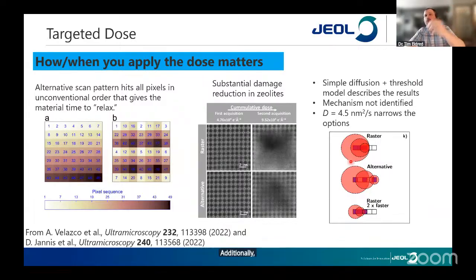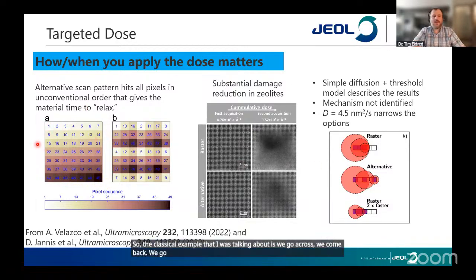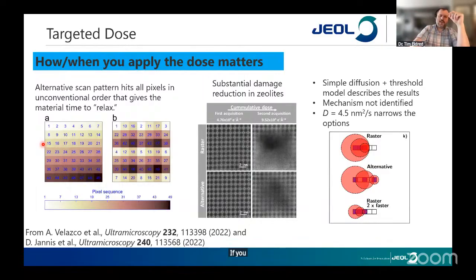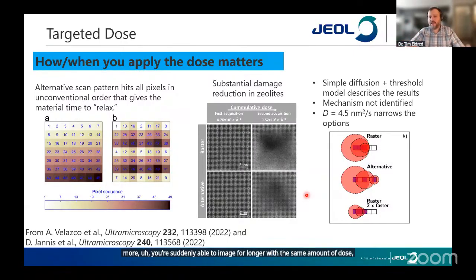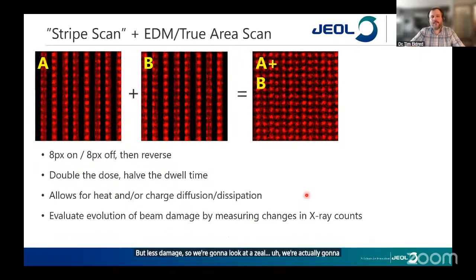Additionally, how you actually move the probe matters. So the classical example that I was talking about is we go across, we come back. We go across, we come back. If you instead go 1, then 2, then 3, 4, 5, 6, there's nothing inherently required about this type of scanning. And what they noticed is by changing where you apply your dose at any given time, you allow the sample time to relax. It allows any thermal issues to diffuse. And so you're suddenly able to image for longer with the same amount of dose, but less damage.